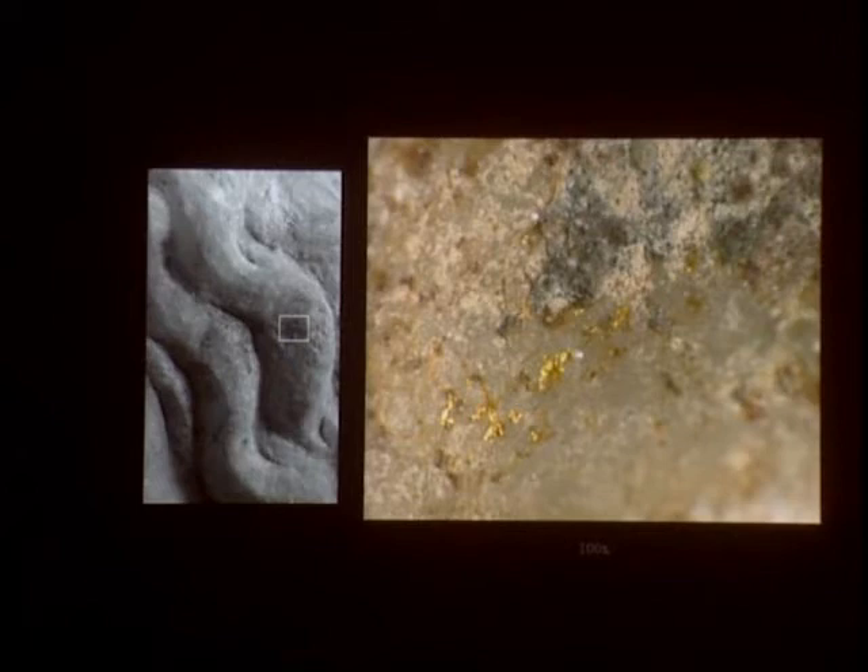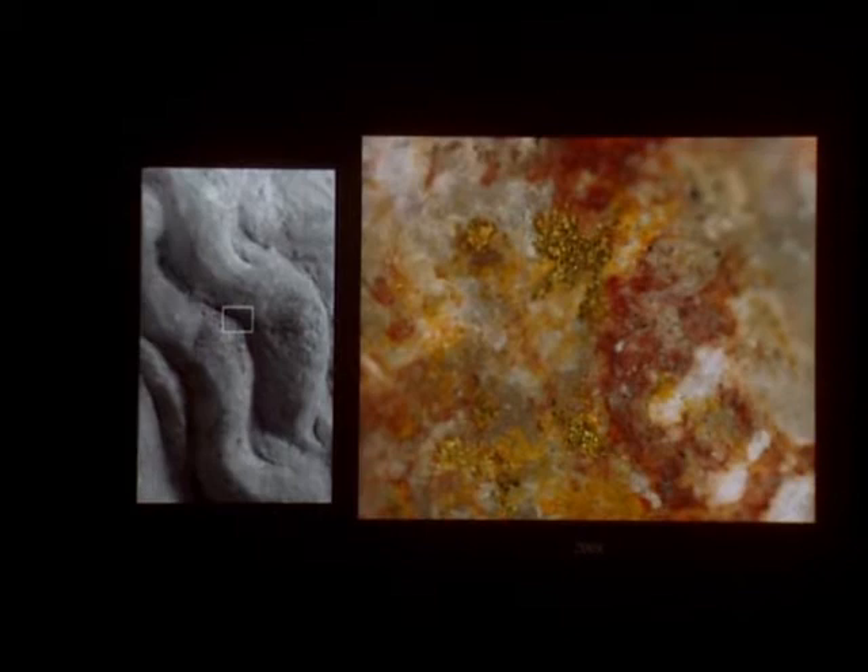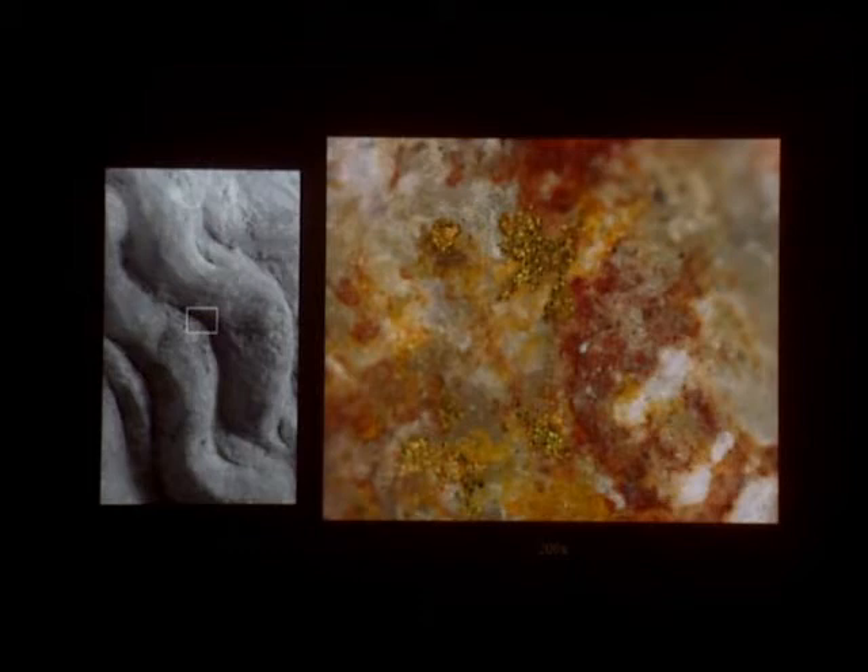This is disparate burial accretion, and we'll see more of a similar phenomenon. Analysis by polarized light microscopy, X-ray fluorescence spectroscopy, and Raman spectroscopy indicate the yellow pigment is a form of yellow ochre. Here you see areas of yellow ochre and areas where the gold leaf is preserved on top. At 200 times magnification, we have areas of modern abrasion exposing the white marble underneath, areas where the yellow ochre pigment applied directly to the marble is preserved, then on top of that the gold leaf, and then — to my surprise — red pigment as well. Then more burial accretion, such as here.